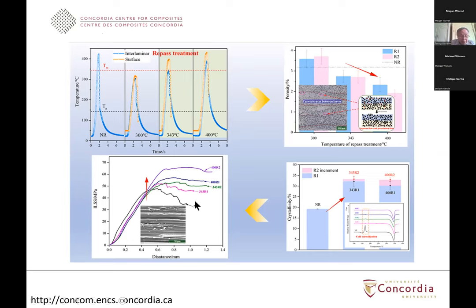For the reference laminate, you have a low value. And if you do that at 343 degrees centigrade, you hit this curve at 343, 400, and 400 two times. So what they mentioned is that you need to have the temperature at the interface more than the melting point to have the benefit of the repass. And so this is the interlaminar shear strength. And the same thing in terms of the decrease in the porosity. The porosity goes down, and also the crystallinity goes up if you follow that kind of procedure.